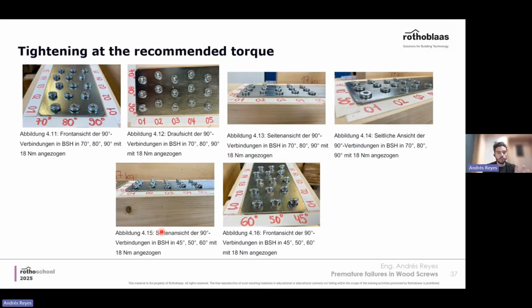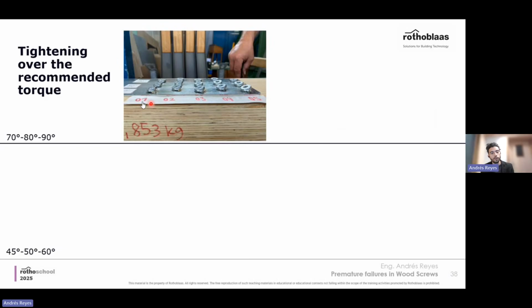These are the results. When you screw at the recommended torque, you see that even at 80 degrees, so a misalignment of 10 degrees, can be recognized easily. Then of course at 70 degrees and more than that, it's preposterous, I would say. But this is more or less what 10 degrees would look like. Once you get into tightening after the recommended torque or over the recommended torque, in many cases you won't be able to see the difference between an 80 degree and a 90 degree because the screw bends and the surface of the head gets fully in contact with the surface.